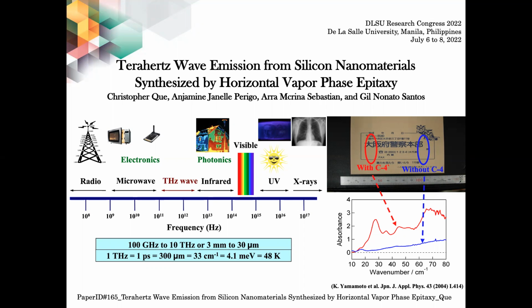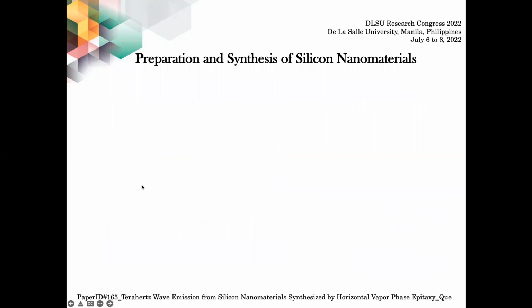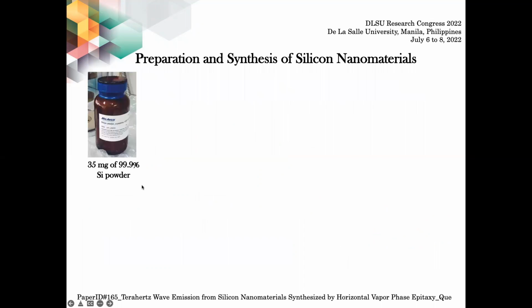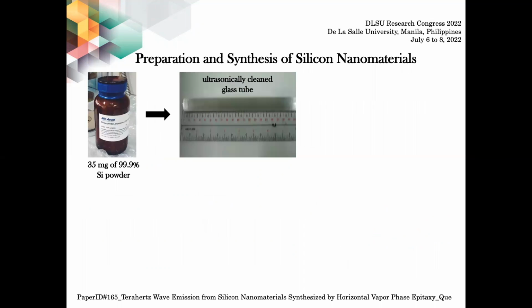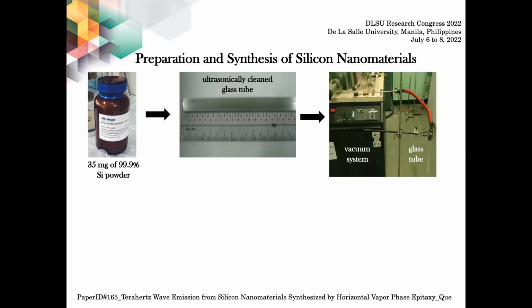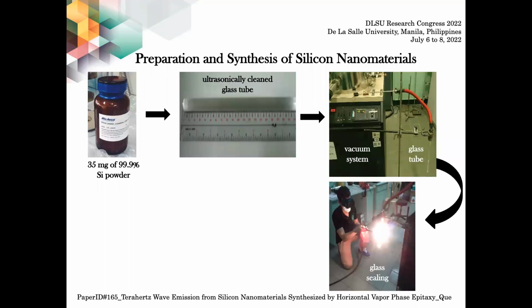In this study, we fabricated silicon nanomaterials using a more economical method, the horizontal vapor phase epitaxy. 35 milligrams of 99.9% silicon powder were placed inside a glass tube that was sealed on one end and ultrasonically cleaned. The open end of the glass tube was then inserted in a high vacuum system and evacuated up to around 10 to the negative 6 Torr pressure. Maintaining the pressure, the open end of the glass tube was then sealed.